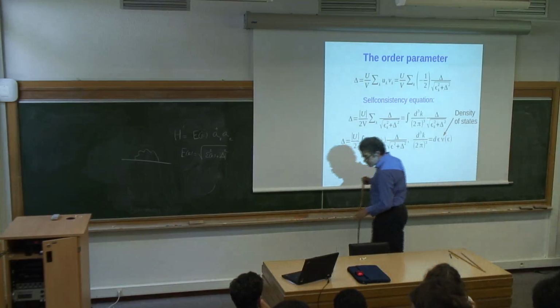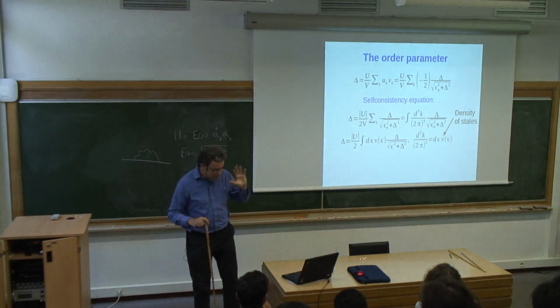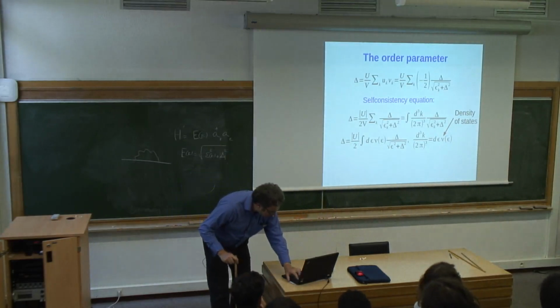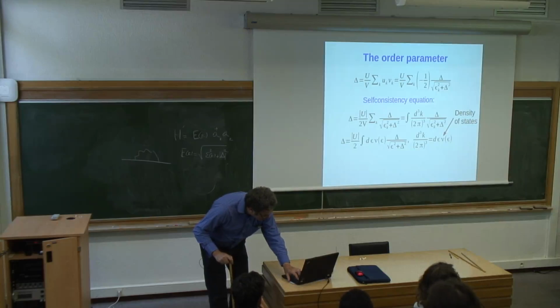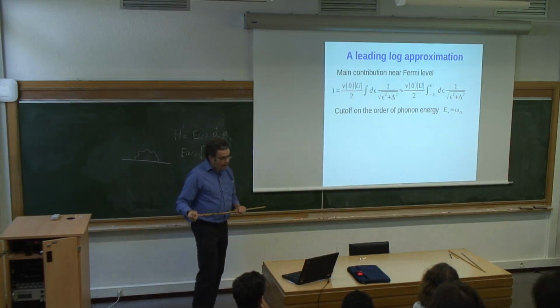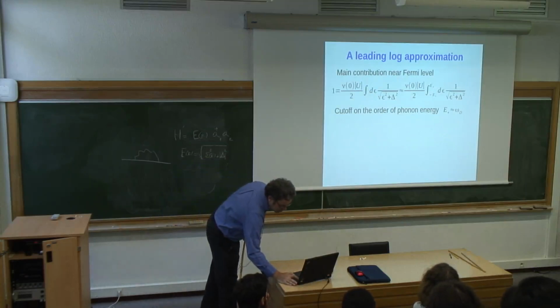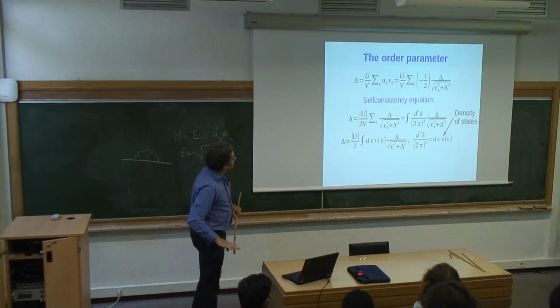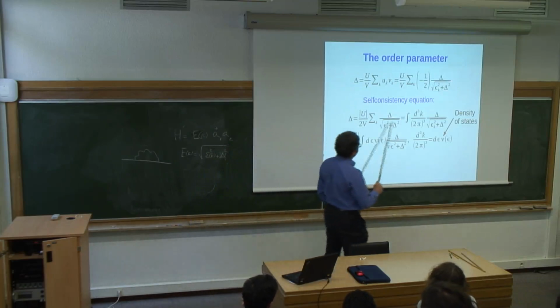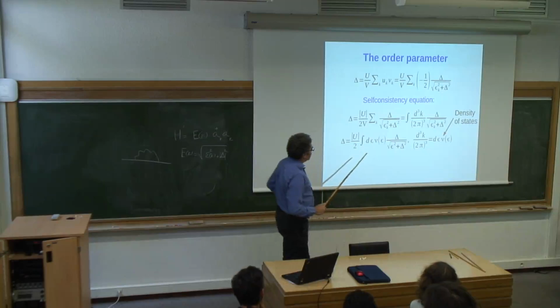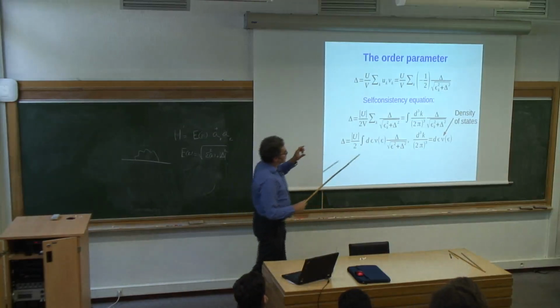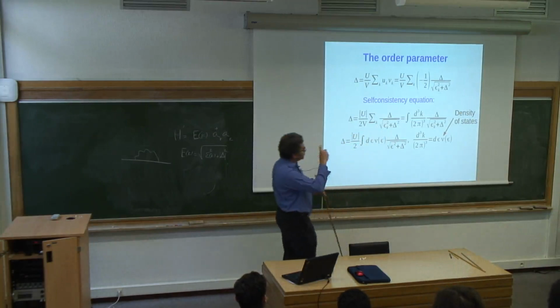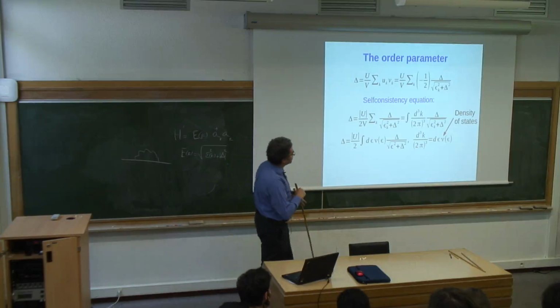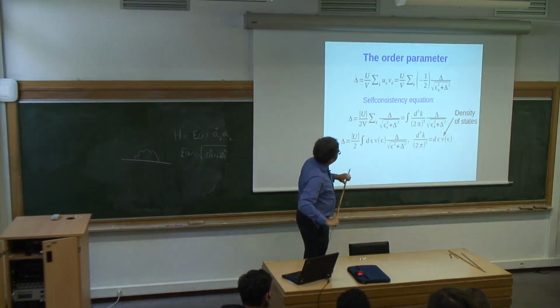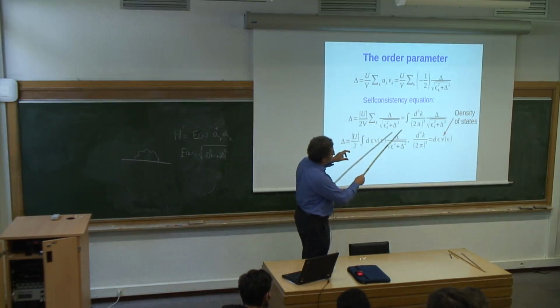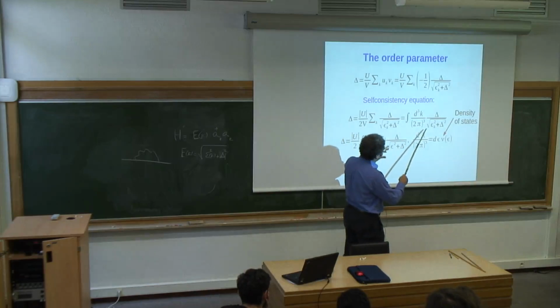And so once we obtained it, too quickly, I admit, we can analyze it and ask what's the solution for this equation. One simple thing we can do is just think about how we evaluate the sum. One realization is that, because of what we said before, that the superconducting gap is going to be much smaller than the Fermi energy and all other characteristic scales for particles, only states near the Fermi level are going to play a role, and states far away from the Fermi level don't contribute too much.